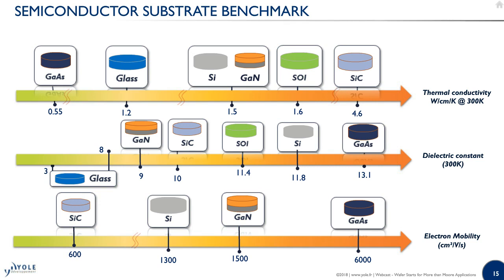and device availability. So if we compare briefly the key parameters or features of the different substrate types available on the semiconductor market, you have, for example, gallium arsenide, which exhibits the highest RF mobility. It has high breakdown voltage, low RF loss, but it has poor thermal conductivity. Silicon, which is the mainstream semiconductor material, has low resistivity, so you have some limitation for RF devices, and it cannot compete at the high frequency range.